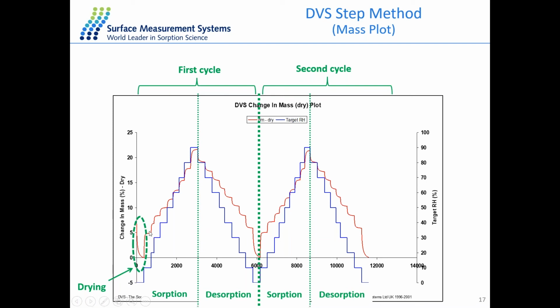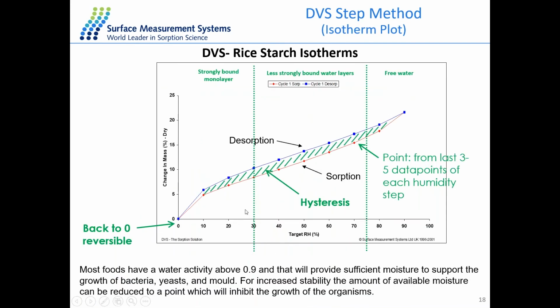And we can take the equilibrium mass content of the material at each humidity, and then we can plot this equilibrium mass change against the target relative humidity. Then we will get this water isotherm for the rice starch moisture sorption and desorption. So the red line is for the sorption branch, and the blue line is for the desorption branch.